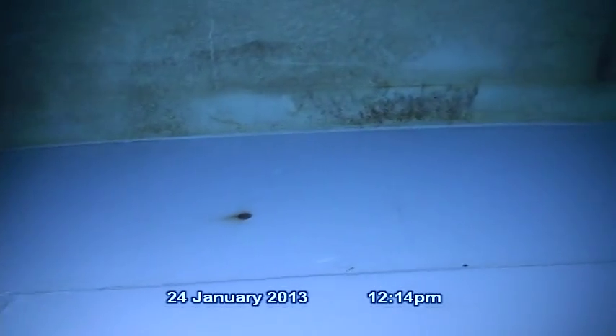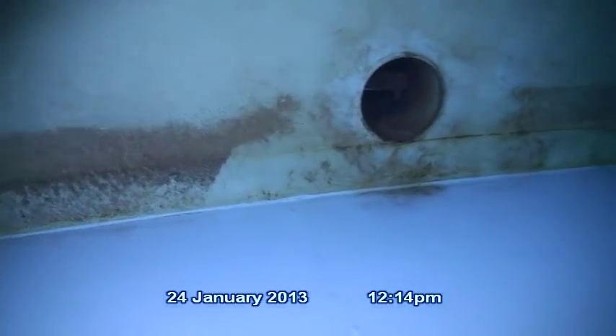The slight and moderate metal loss seem to be taking place in areas where medium-sized to large corrosion nodules are located on the floor. Approximately 150 of these areas are located on the floor. Until the facility can be recoated, we do recommend addressing the areas of metal loss. The loose sediment and debris has been removed from the floor around the outlet line.